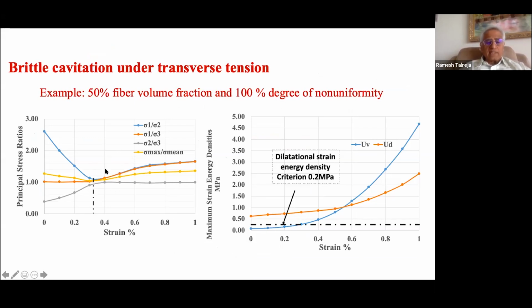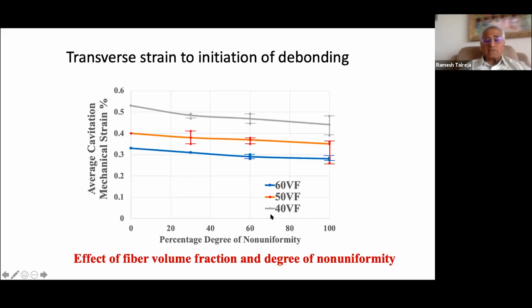So what we do essentially is to look for the right conditions, three principal stresses being equal. We plot the ratios of it, and at applied strain of approximately 0.3%, the three principal stresses become nearly equal. And then we look at how with the applied strain, the maximum dilatation energy and distortion energy values are changing. And we find that before you get to this point, you have already satisfied the minimum criterion. That's a criterion for minimum energy density for dilatation. So that happens in transverse crack formation.